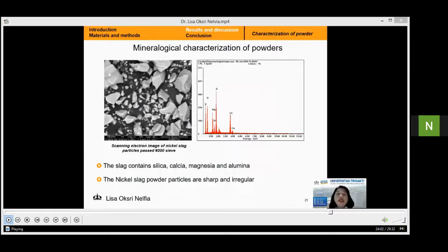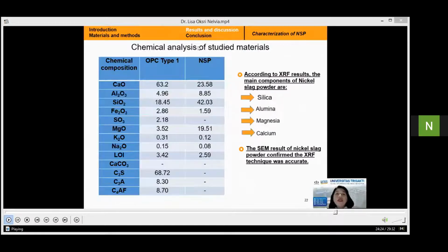About the mineralogical characterization of the powder, a scanning electron microscope image of the nickel slag is presented in this figure. It contains silica, calcium, magnesia, and alumina, and it shows that the slag particles are sharp and irregular. The result of chemical analysis by X-ray fluorescence technique confirms the SEM images about the main components of nickel slag powders.